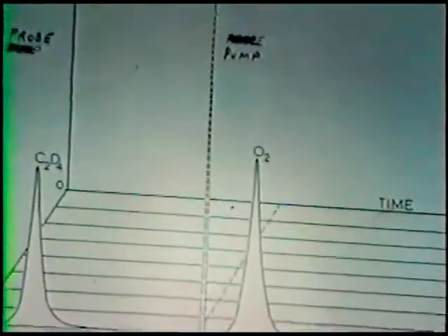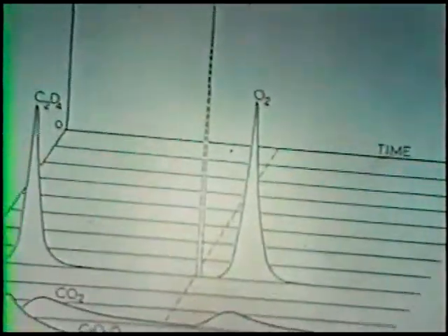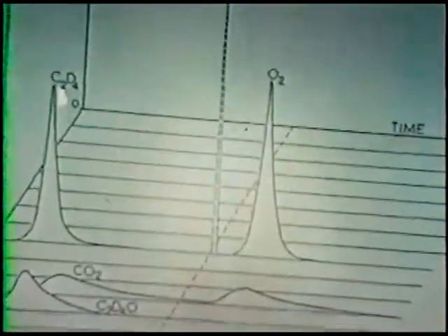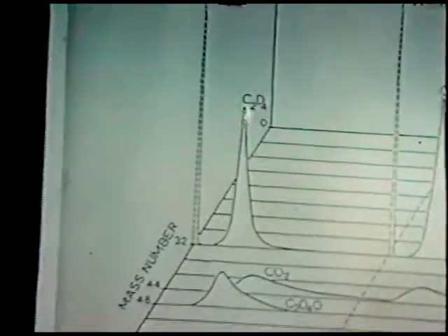But then there are flight times. There is this oxygen pulse that comes through the reactor. Then after that, at some time t, the pulse of ethylene can be sent into the reactor, and one sees the products come out. So we can vary the time delays between these pulses and load the surface with oxygen, and then at varying times send in the ethylene pulse to see what the characteristic time is for the surface species that's giving rise to ethylene oxide.